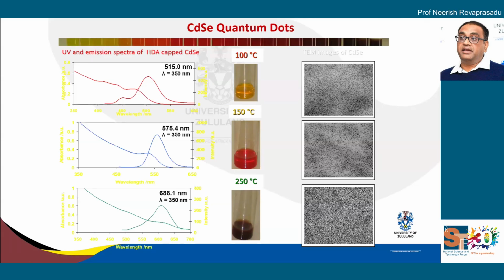So these excitonic features are very indicative of small particles. And then if you increase the temperature, from 100 to 150 and 250, you can see the emission moves more red. So from 515, it goes to 688, right? And you see the excitonic features sort of flatten out. You don't see very distinct excitonic features. And then you can see them obviously with the electron microscope. You can view the particles. They are very small and very distinct. And you can see the color changes, from a light to a darker color, purely based on size.